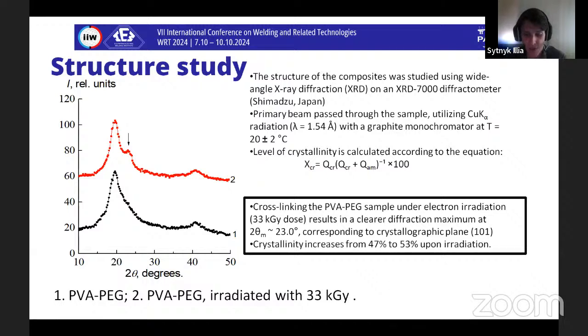The analysis of wide-angle X-ray diffractograms of the initial PVA PEG sample and irradiation cross-linked PVA PEG samples showed that the cross-linked sample, which was exposed to the irradiation dose of 33 kilogray, has a more clearly manifested diffraction maximum at 23 degrees, which corresponds to crystallographic plane 101, according to Miller indices. It should be noted that when cross-linking the PVA PEG sample with accelerated electrons, its degree of crystallinity increases from 47% to 53%.